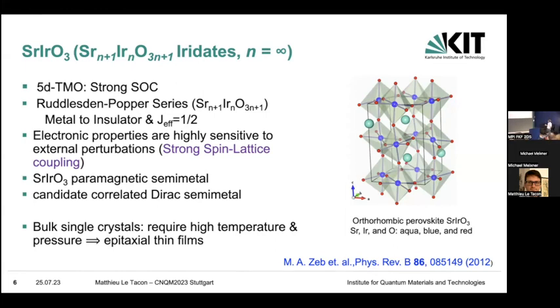As all the other members of the family, generally the octahedra here are quite flexible. They can rotate a lot and modulate the electronic wave functions and the magnetic coupling here. So the properties are generally strongly sensitive to the lattice and to elastic coupling. But the strontium iridate 113 happens to be a paramagnetic semimetal, which has some Dirac points in its electronic structure, a bit far away from the Fermi level, something like 150 to 200 milli-electron volts away. But still, the idea is that they could be driven to the Fermi level and give rise to a correlated Dirac semimetal.